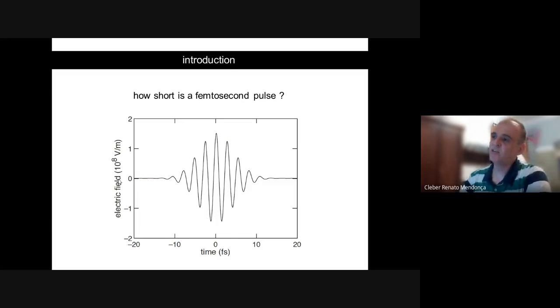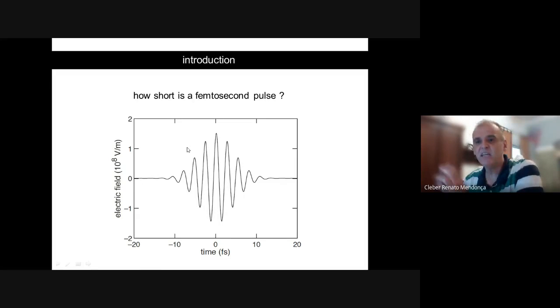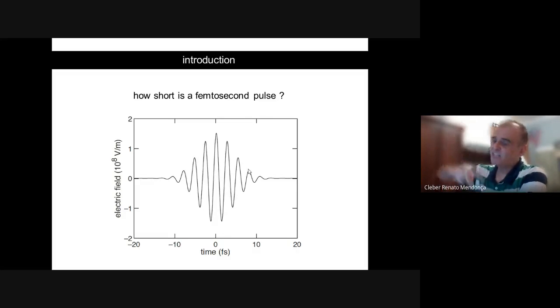Another illustration that I like to use to express how short a femtosecond is is this one here. In this picture, I'm showing the electric field of a femtosecond laser pulse at 800 nanometers, so in the near infrared. As you can see, this pulse goes from minus 10 to 10, so it's about 20 femtoseconds in duration. At 800 nanometers, it means that the electric field only has time to oscillate 1, 2, 3, 4, maybe 7 times. So when we are talking about electromagnetic waves in this femtosecond domain, the femtosecond laser is not a wave that oscillates a lot. It doesn't have time to oscillate several times. For these 20 femtosecond pulses, the electromagnetic wave only oscillates a few times.